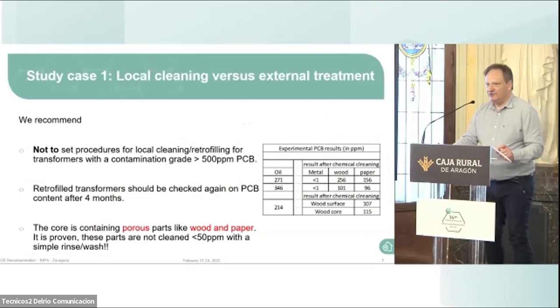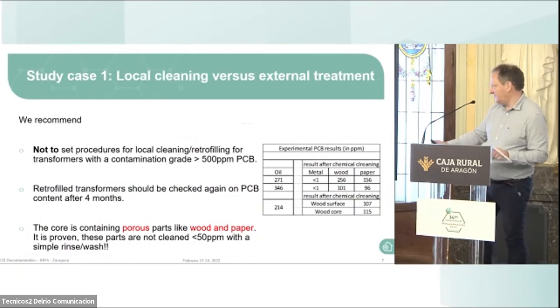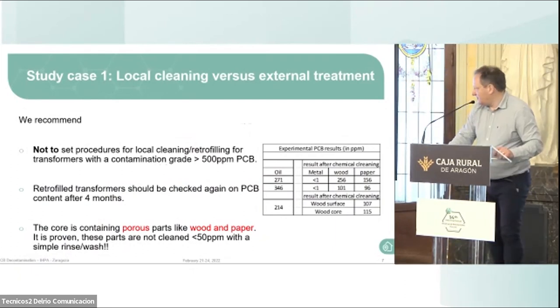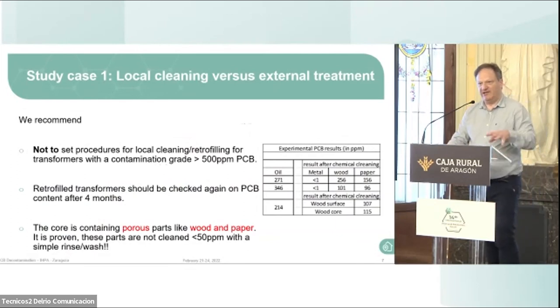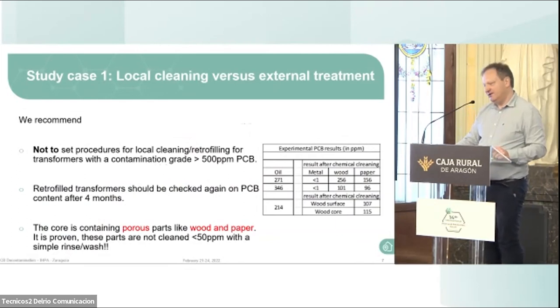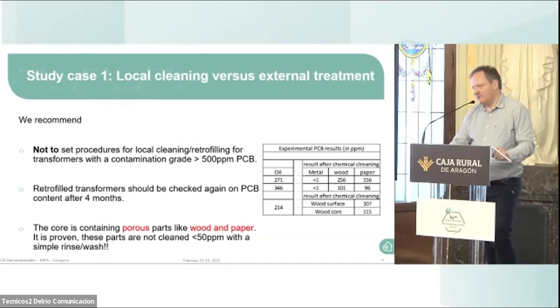I would like to come back to the porous materials. So we are receiving PCB transformers. We check the oil, measuring the PCB content, and in the left column you see the PCB concentration in the oil. We take out the core, we clean the metals and so on in our machine. What we see is that the residual PCB content on the metals was fine, below 1 ppm. When we take samples of the wood or the paper, we are not reaching 50 ppm, even with our system, even with the solvent, even with the temperature, even with the high pressure, with the vacuum and so on. We are not reaching the 50 ppm threshold value for PCB contamination.